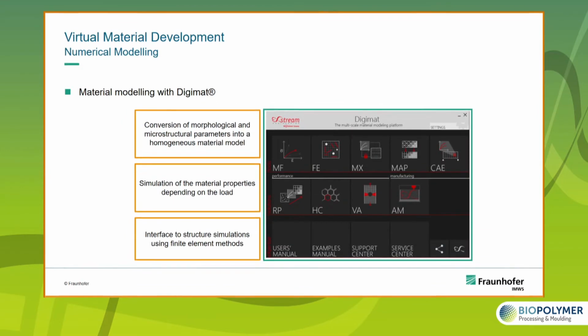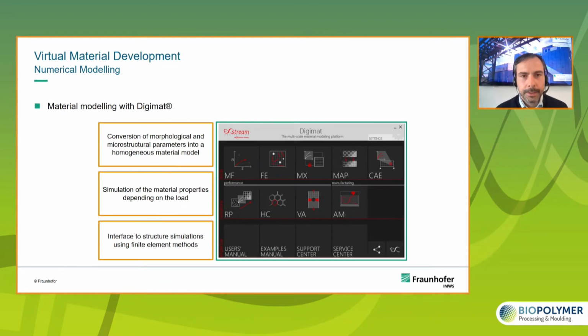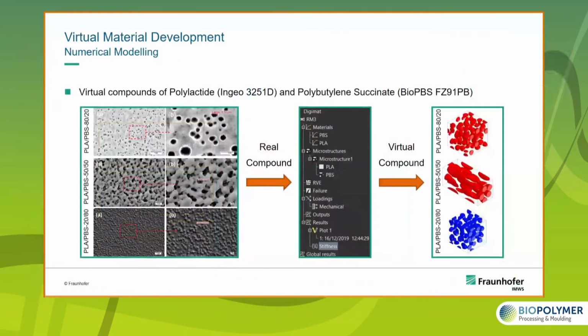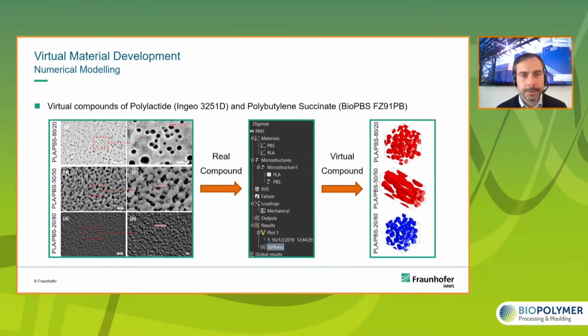This step is done with the software Digimat. In Digimat, you can define your own material, your own microstructure of your material, and then transform this into a material model, and finally predict material properties by numerical simulation. How this looks, you can see here. On the left side, you can see the microstructure again of our PBS PLA blends with different compositions. At the top, you see the blend with a composition of 80% PLA, 20% PBS, in the middle 50% PLA, 50% PBS, and at the bottom 20% PLA and 80% PBS.